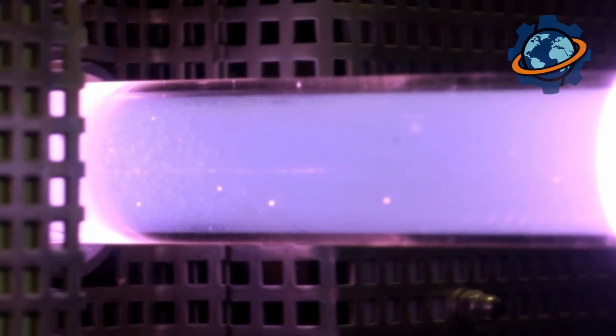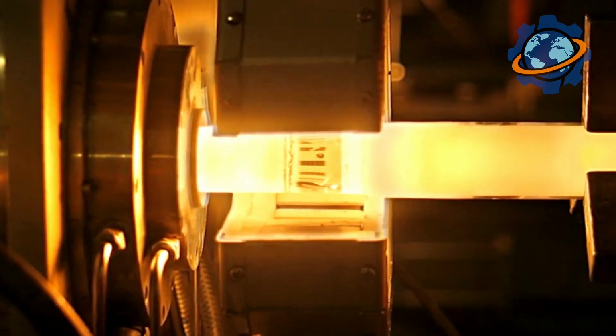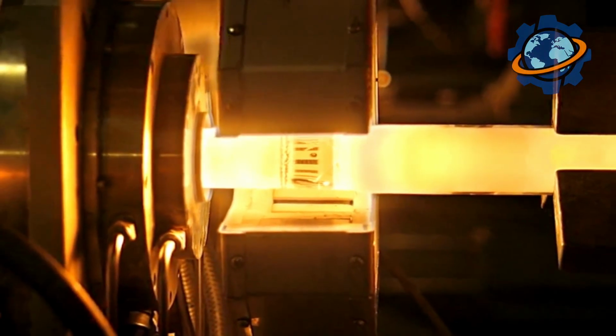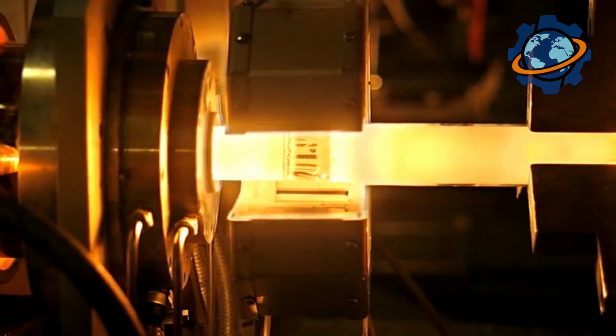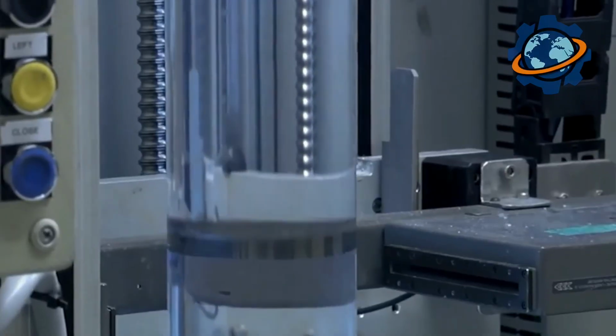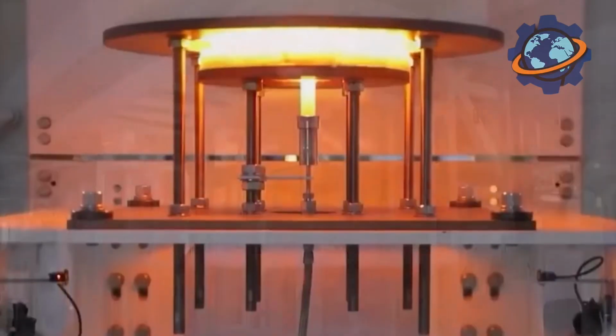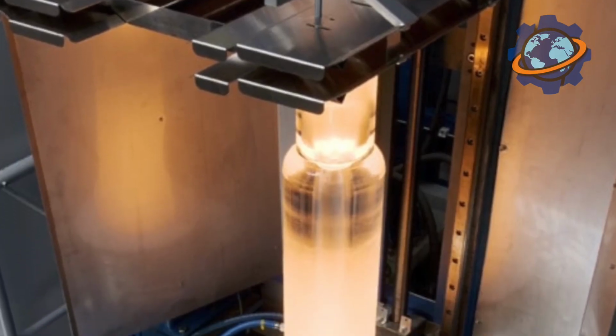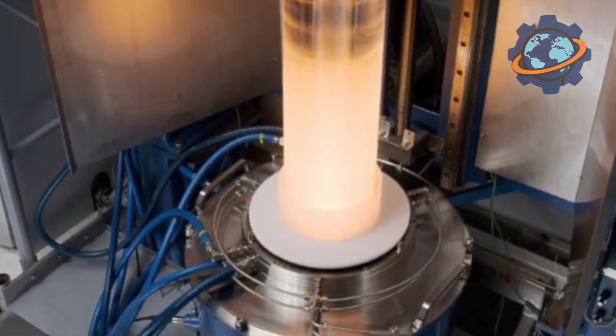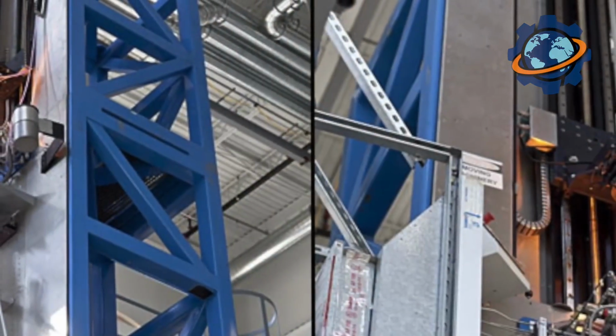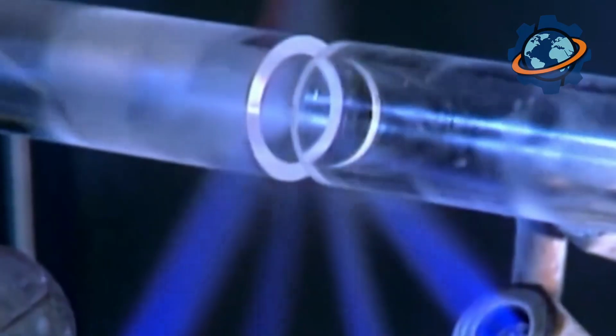These vapors hit the inner surface of a transparent tube, which is heated very intensely. When the vapors touch the hot wall of the tube, they deposit and turn into tiny droplets of glass like dew collecting on leaves in the morning. Gradually, these droplets collect, layer by layer, until a thick layer of glass forms inside the tube. Then this tube is heated even more intensely, and it collapses into a dense solid rod, and this is our preform.